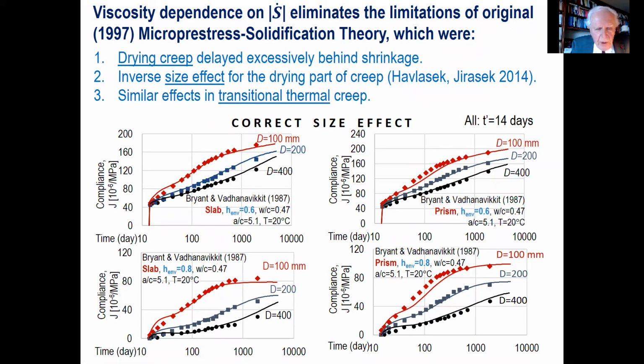Now I show where we could not fit well before, getting the reverse side effect, at least for part of the time. Extended experiments of Bryant, which show for different thicknesses, for different concretes. You see this is 100, 200, 400. And you will see we fit the side effect very well.